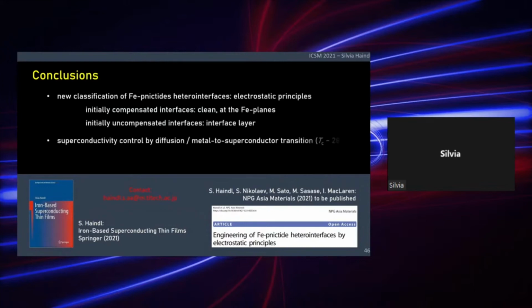You have seen now a new classification of iron pnictide heterointerfaces, which is based on electrostatic principles, and we can classify the heterointerfaces into clean ones, which are initially compensated interfaces and which appear at the iron planes, or interfaces that show interface layer formation. These are the initial uncompensated interfaces. You have seen that the superconductivity in the iron pnictides can be controlled by diffusion. We can also see metal to superconductor transitions with quite high TC of 28 Kelvin. And finally, I have shown you an example of a film substrate interface and how it determines the film roughness in ultrathin films.